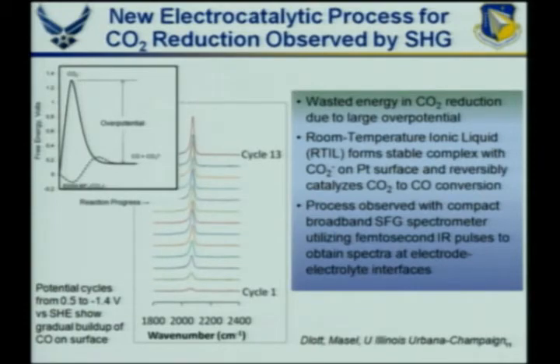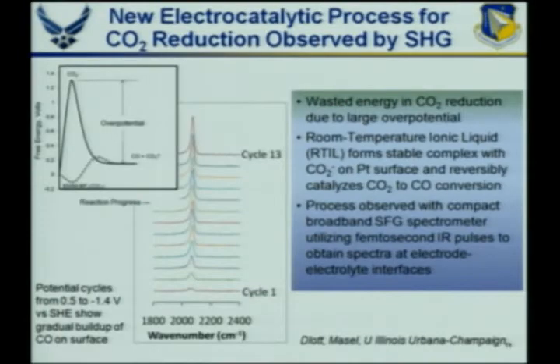Another example of some probing of these intermediates in CO2 reduction is some work done at the University of Illinois. Again, some of the experimental work, the synthetic work, was done by Rich Masel. And again, as I mentioned, if we can just go from CO2 to CO, that would be an important step. We can make what's called syngas there and produce fuels. But as you can see, there's a very high barrier to doing that. In electrochemical terms, that's called an overpotential. That's wasted energy that you have to put in to make that happen. It would be nice to try to reduce that barrier. And again, a catalyst is what we can use to reduce that barrier.